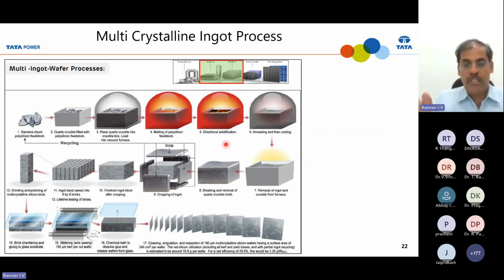So whatever silicon is in contact with the crucible, close to that area, the quality of the silicon material is very poor, because a lot of contamination comes from the crucible wall through solid state diffusion. So the contamination is very high. So only the center portion of this complete ingot will be better, and in this area, the edges close to the wall, the quality is very poor. If you convert this area into wafer and use it per cell, the minority carrier lifetime will be very poor. The conversion efficiency also will be less.